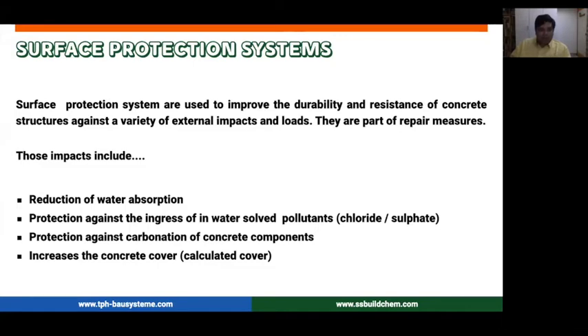So what they basically do is they work with things like reduction of water absorption. They protect against the ingress of waterborne pollutants like chlorides or sulfates or things like that. What they basically do is they increase the concrete cover. That means in terms of durability, maybe say 300 microns of a particular coating might be equivalent to almost about 70 to 80 centimeters of concrete, or like M30 concrete. So it gives you a very high degree of protection.